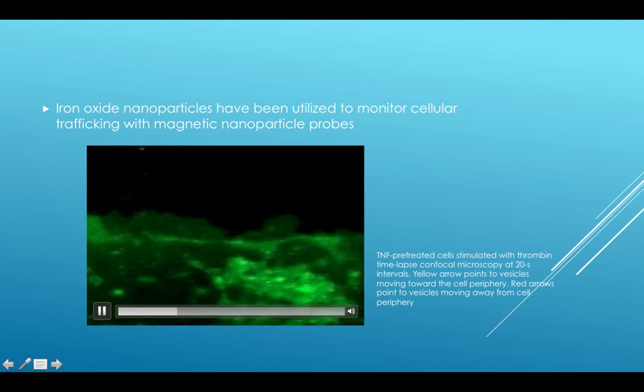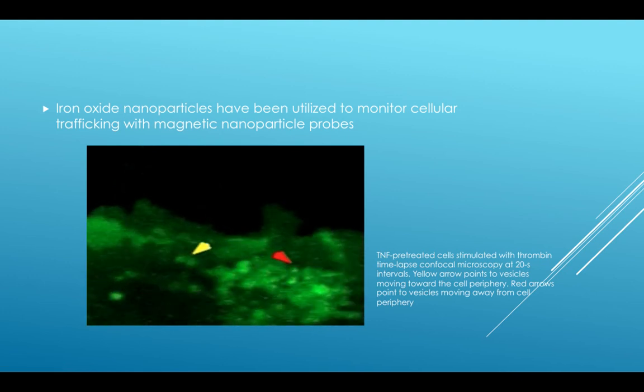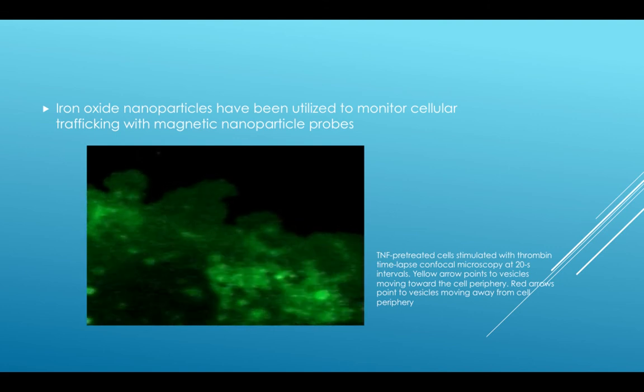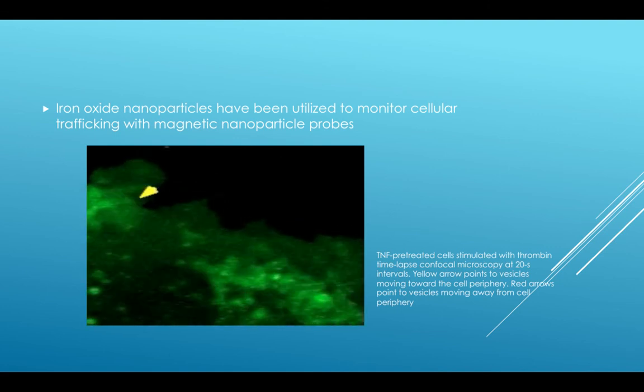Magnetic nanoparticles such as that of iron oxide, between the sizes of 2 and 20 nanometers, display superparamagnetism, a form of magnetism that appears in small ferromagnetic particles. These particles can produce intense magnetic fields that leave no magnetic memory on the nanoparticle or surrounding tissue. This process has been utilized as a means of magnetic sensing probes for in vitro diagnostics.